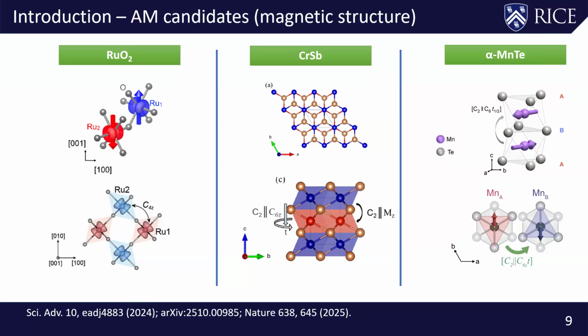So this is now basically confirmed to not really be an altermagnet. The other example believed to be an altermagnet is chromium antimony. In this case, the system is hexagonal. It's collinear, with the moment along the z-axis direction, and in this particular geometry you actually do not expect anomalous Hall effect. Neutron measurements have shown a band splitting, suggesting it could be an altermagnet.